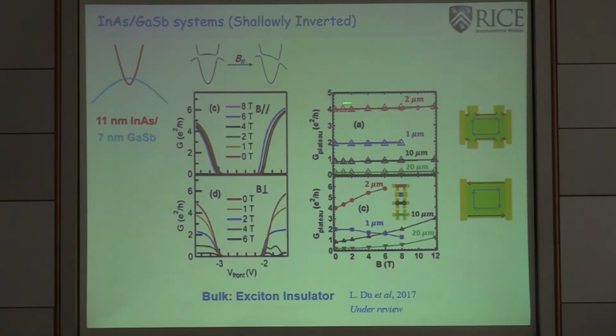One can find that the edge state conductance shown here remains pretty much the same for different sizes of samples. This is from 0 all the way to 12 Tesla, and the conductivity basically remains flat for all these samples, or for different lengths.